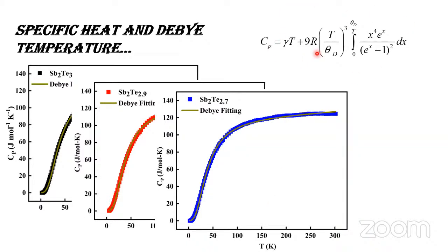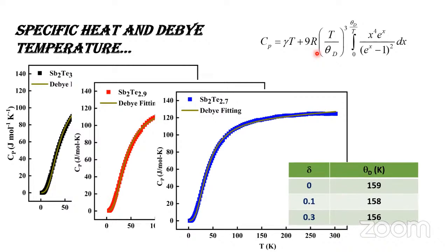The well-known Debye equation, and from this equation, we can get the Debye temperature for all the samples. And you can see that the Debye temperature is decreasing with increasing incorporation of Te vacancy. This is due to the increasing defects in the tellurium vacancy Sb2Te3 system.